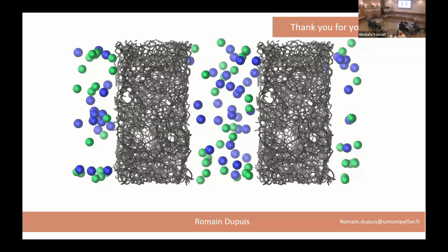So I think that's something that will play a big role. And another role that will be important is the chemistry, because when you have defects here, you can have terminations that are carbon terminations that can react with water. So it can make OH groups, or it can make COH or CH, or things like this. And that might play a very big role in the adsorption of the ions also. Okay. This we don't really take into account yet, but we will try to understand more.